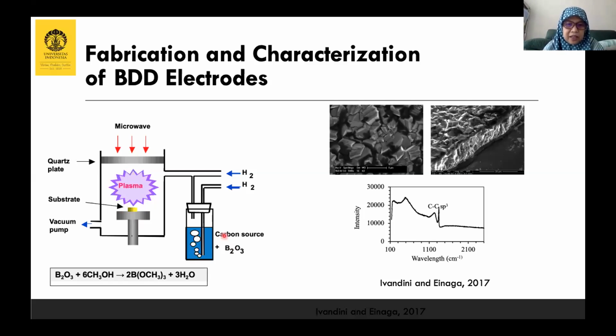And if in the carbon source we put a small amount of boron, we will have boron doped diamond. Here is the same image of boron doped diamond. As you can see, generally the particle size is 5 micrometers, and the thickness is about 5 micrometers also.